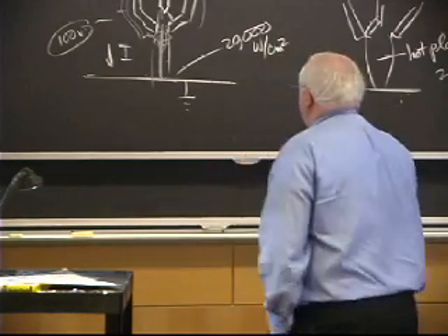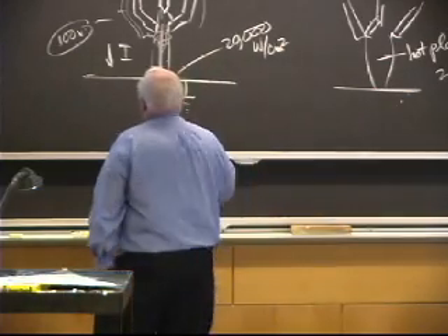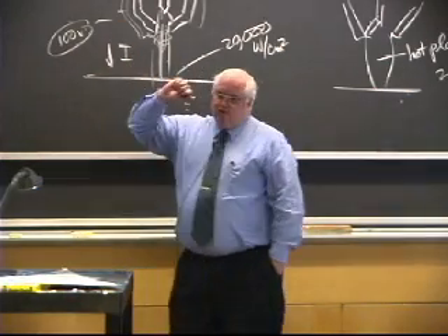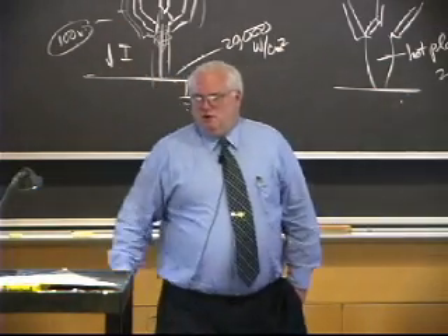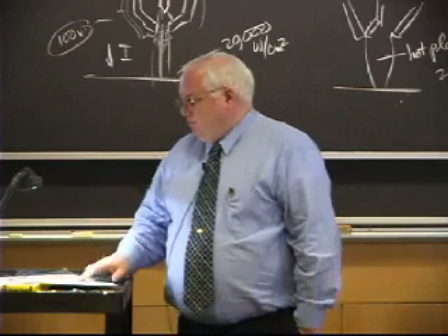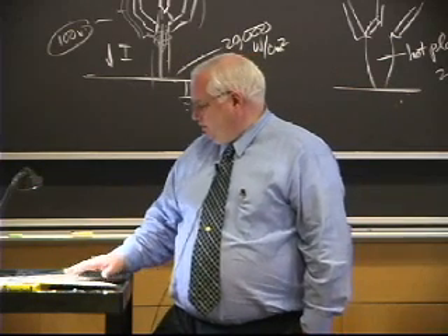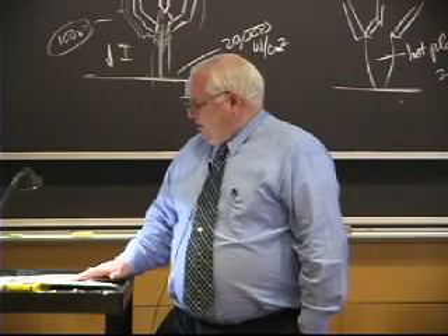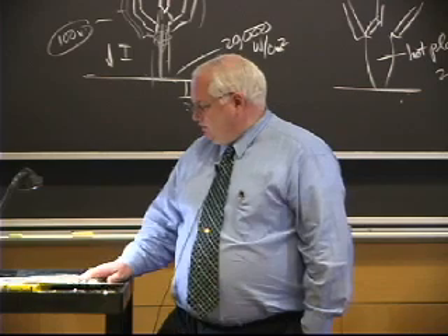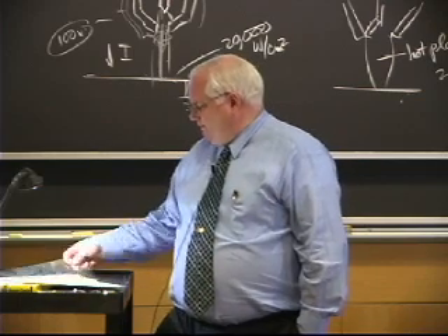In fact, the open circuit voltage on the power supply can be 400 volts, whereas the open circuit voltage on the welding power supply is probably only 100 volts, and once you draw much current, it's down to 30 volts. So that's transferred, non-transferred plasma arc.